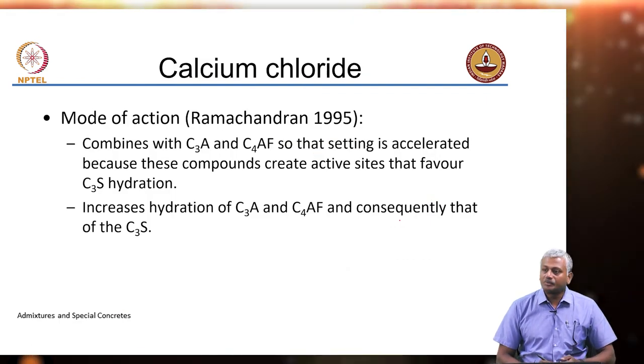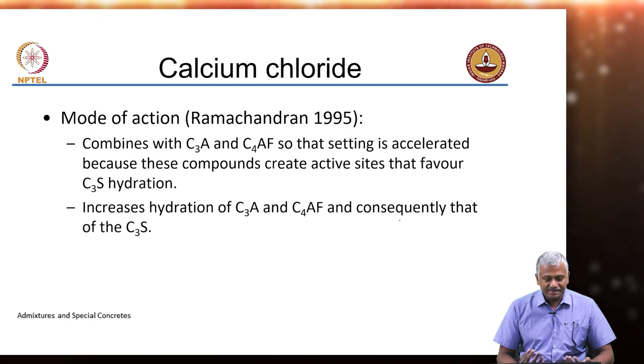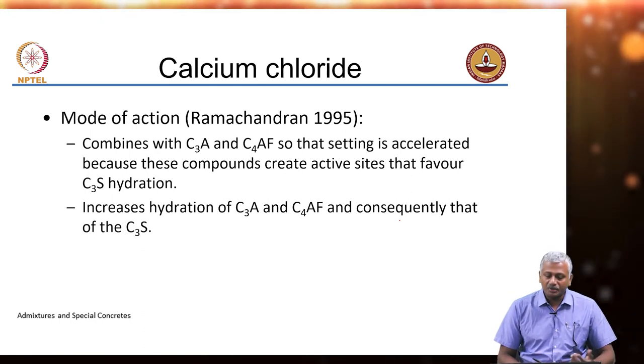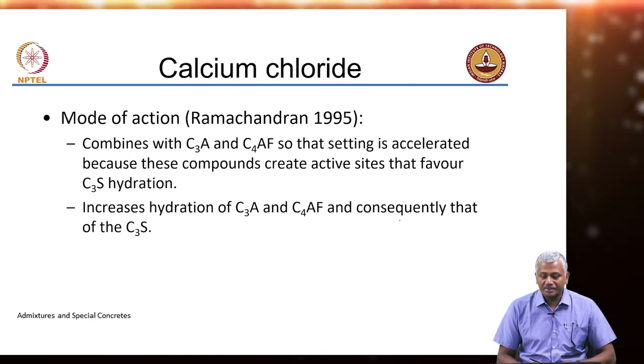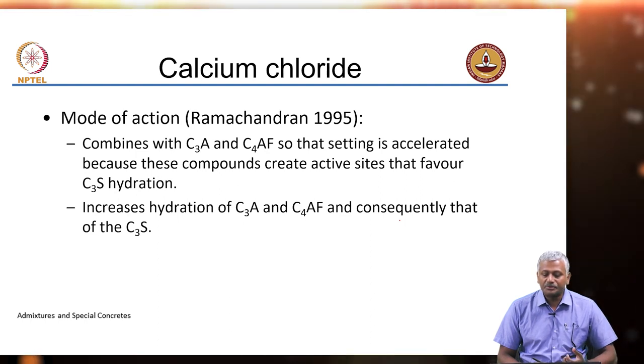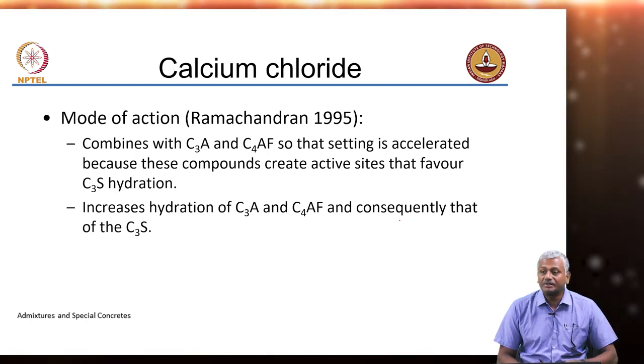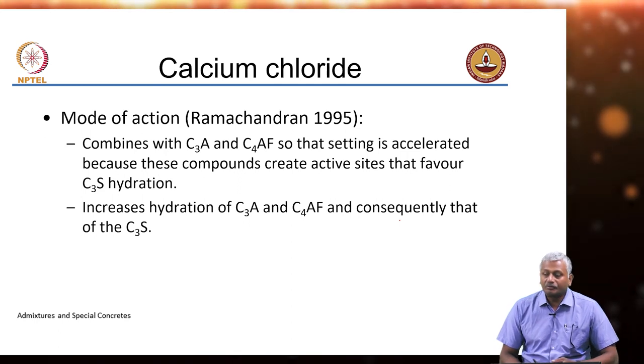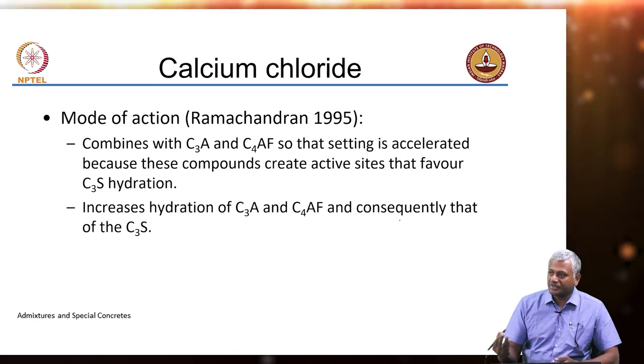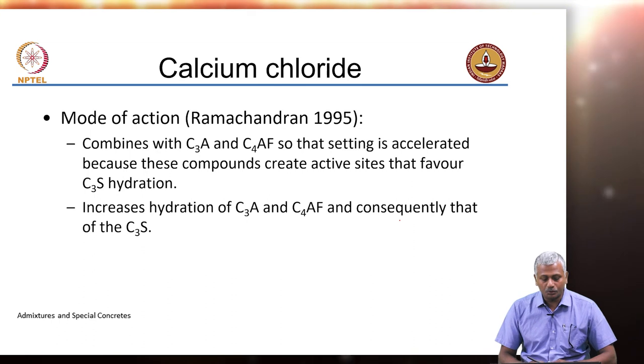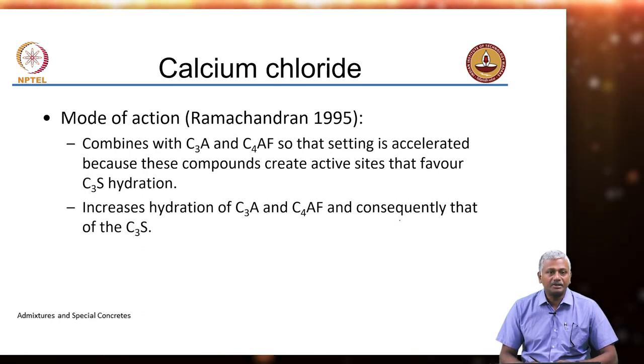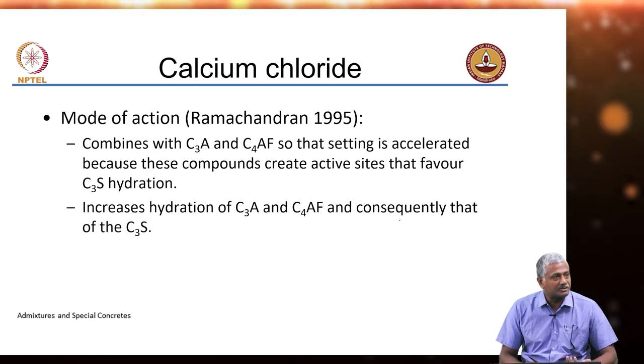Now, calcium chloride - people have done extensive studies on it. It combines with your aluminates, so that setting is accelerated because these compounds create active sites that favour C3S hydration. And secondly, calcium chloride increases the rate of dissolution of the calcium as well as the silicate species.